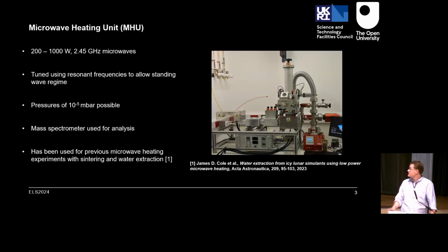So this is the heritage microwave system that we've got. It's been used for a number of years now and designed primarily for sintering experiments, so going to very high temperatures. It can produce 0 to 1,000 watt microwaves at 2.45 gigahertz. So it's a stationary frequency; we can't adjust the frequency. It uses an adjustable tuner, so we can set up a standing wave regime where hotspots occur, and this is where the maximum electric field occurs. So it's where you want to place your sample.